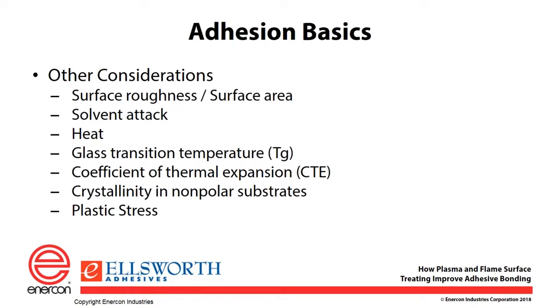Solvent attack is an important thing to recognize. Solvents can be used to actually promote adhesion. So it's not uncommon at all to have a solvent like N-methylpyrrolidone added to a formulation in order to have it bite into the substrate and actually create a better bond to the substrate. Solvents can also be used to clean plastics if you're working with plastics. The important thing to note there is you need to pick your solvent wisely, because solvents will also attack the plastic and craze the surface, and they can cause it to have a dull finish, for instance.